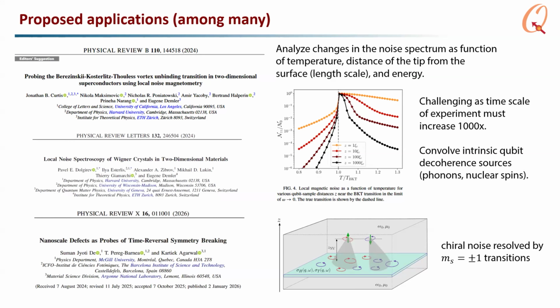Does that have any potential for energy resolution? Or what is expected? Oh yeah, it has great energy resolution actually. For T1 relaxometry, you have to be resonant with the NV center transition. So the energy resolution is basically the line width of the NV center, which is a few megahertz. A few megahertz is essentially like a delta function in energy resolution.